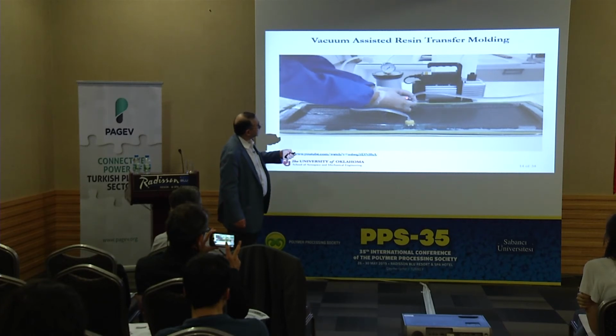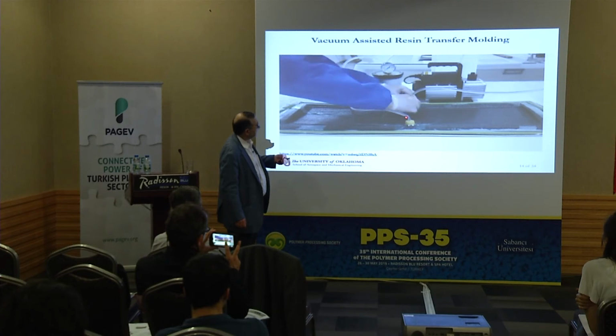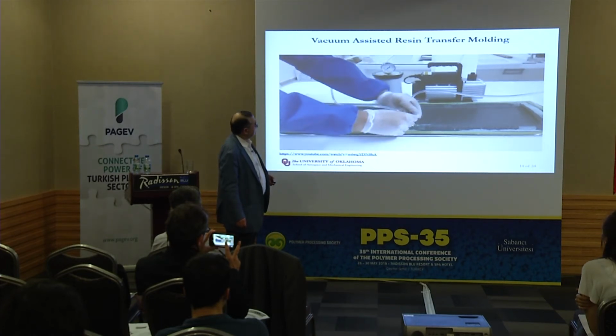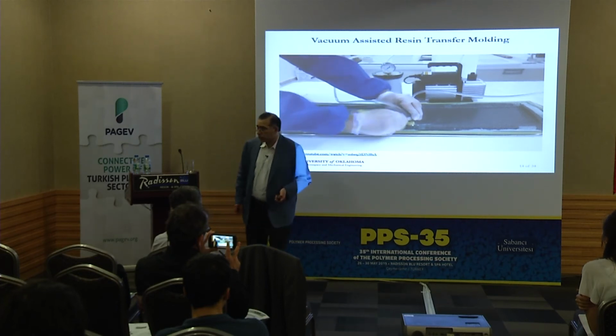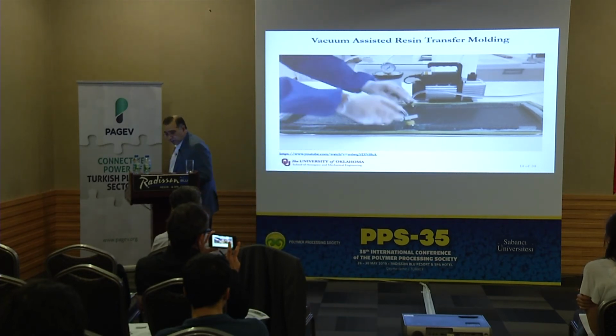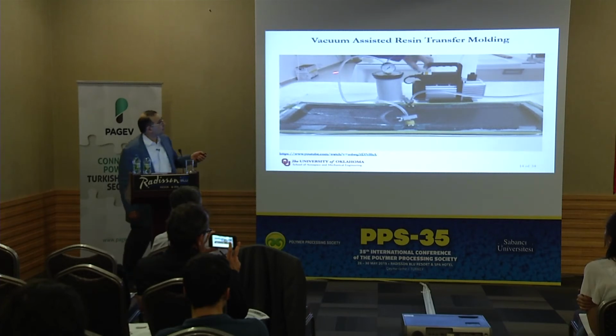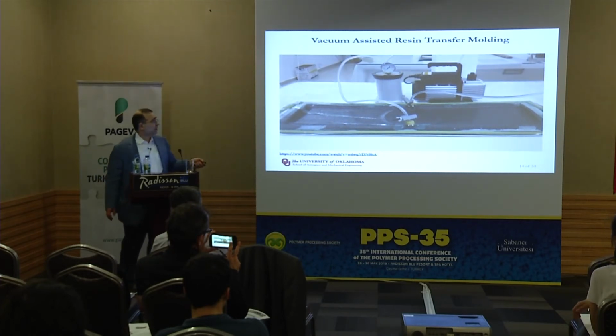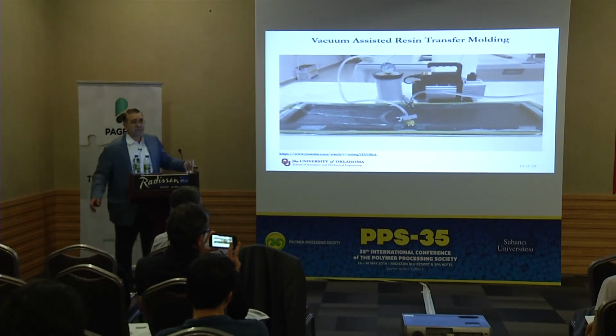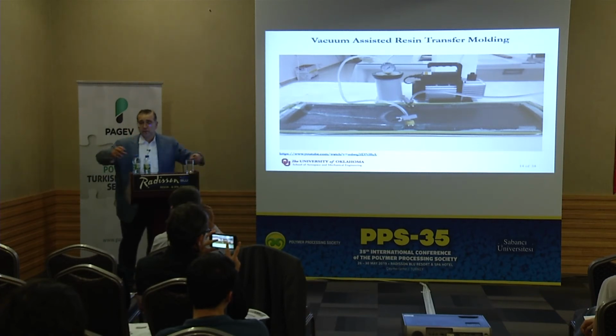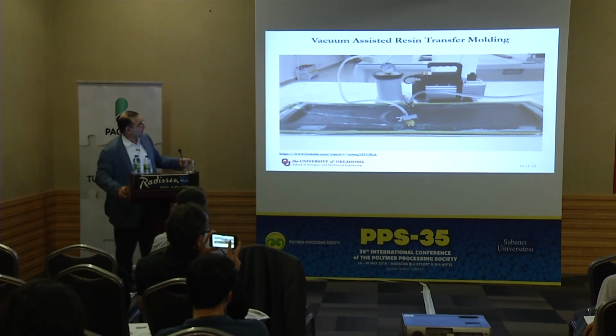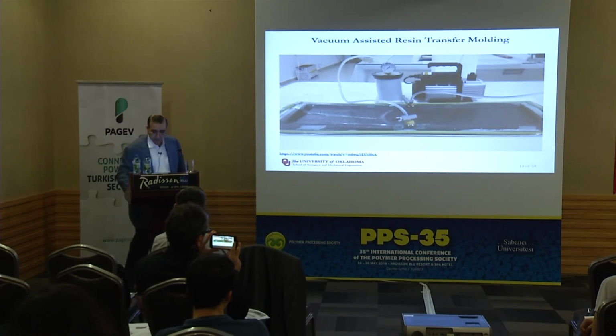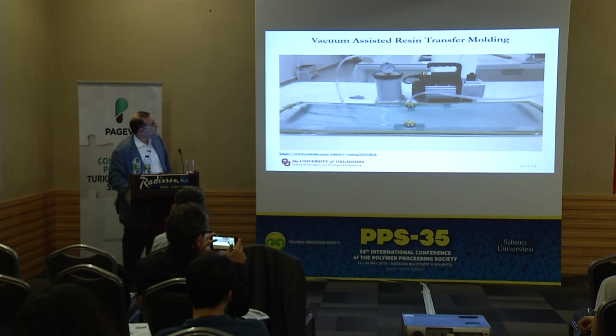And we are clamping the inlet and then clamp the exit and let the part cure. So this is pretty much the basic VARTM process, vacuum-assisted resin transfer molding. You will have multiple inlets when you are doing the wind turbine blade. You have multiple flow channels and all that. And the distribution media might be on top so that the flow is distributed faster.